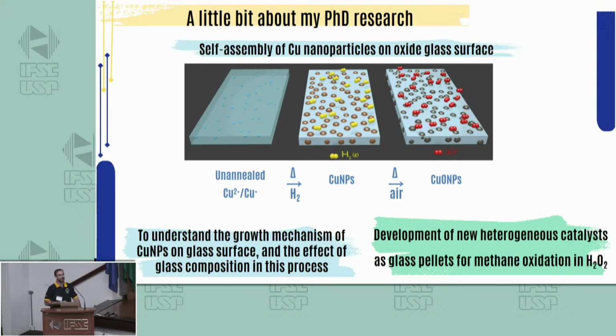So basically, I'm working with copper nanoparticles, and I can grow these nanoparticles on an oxide glass surface. Copper is just like a normal glass modifier, but when we thermally treat this glass in a hydrogen atmosphere, we can grow these nanoparticles, and we can also oxidize these copper nanoparticles. In my poster, I will present some results about the growth mechanism of these nanoparticles by in situ X-ray absorption. Basically, we need to understand how this growth mechanism works and how the glass composition affects this process, and then develop more efficient heterogeneous catalysts, like the glass pellets that I'm working on in my PhD thesis, to promote oxidation in hydrogen peroxide. So thank you everyone for your attention.